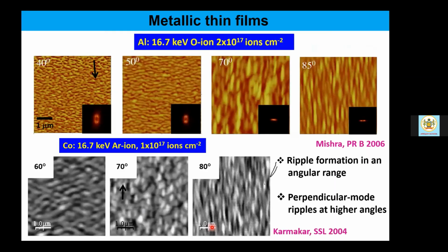Now, these are the examples of aluminium target. Again, ripple patterns are seen. I mean, transition of the ripple orientation is very obvious from 40 to 85 degree. You see here the ion beam projection is along this arrow, and the direction of ripples was perpendicular, but here it becomes parallel as the angle of incidence starts increasing. The lower frames correspond to pattern formation using the same energy of argon ions, but on cobalt target.